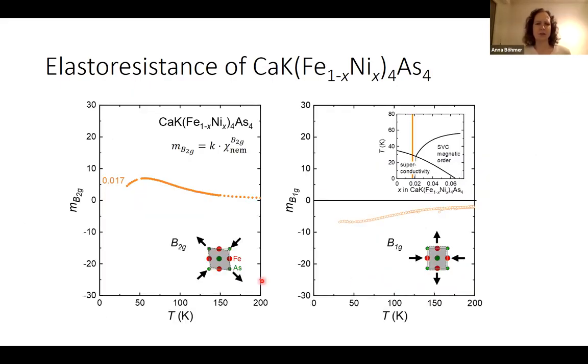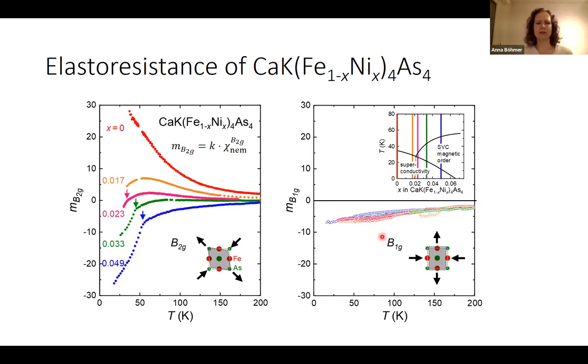So when I do this, here for the one example, the B2G and the B1G elastoresistance coefficients related to these different strains, and that's the doping evolution all over the phase diagram. First of all, the B1G doesn't evolve at all. So it does not depend on the composition. It's unaffected by whatever drives this phase diagram. So there are no interactions there, and we will not look at this one.